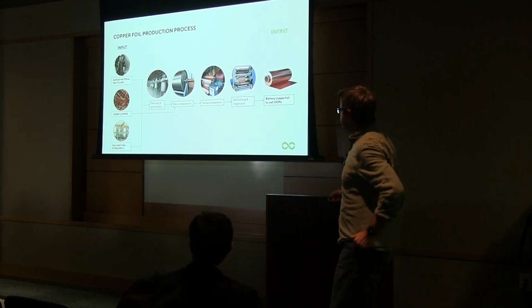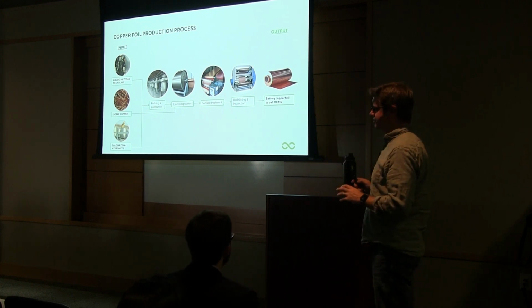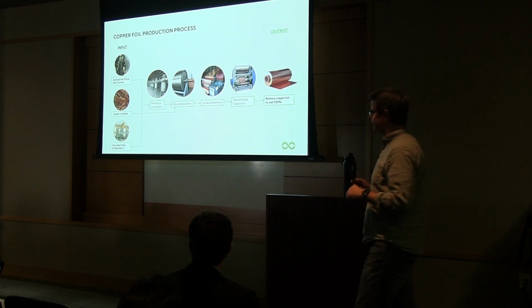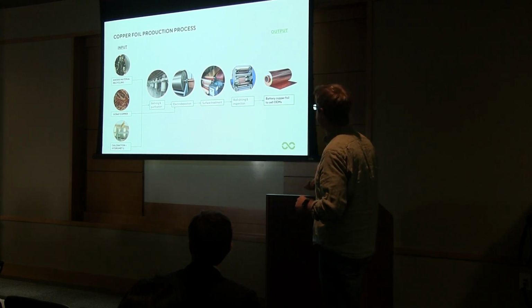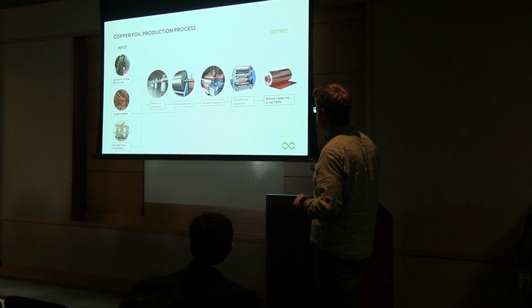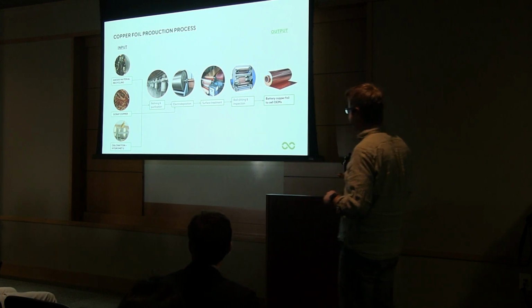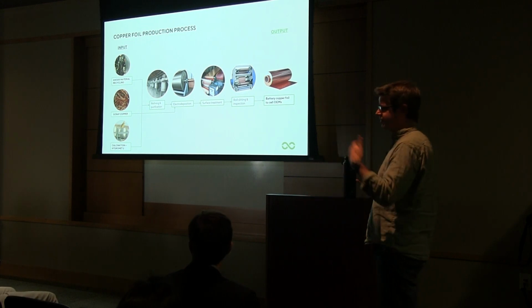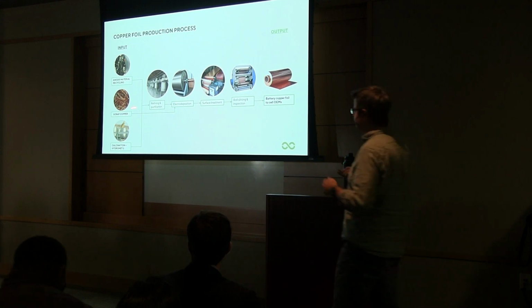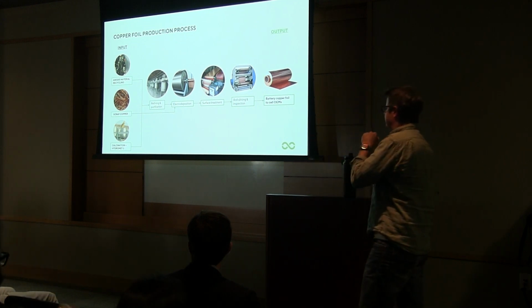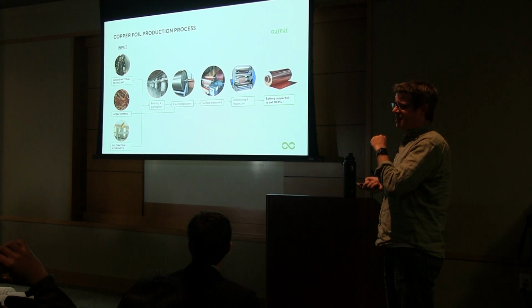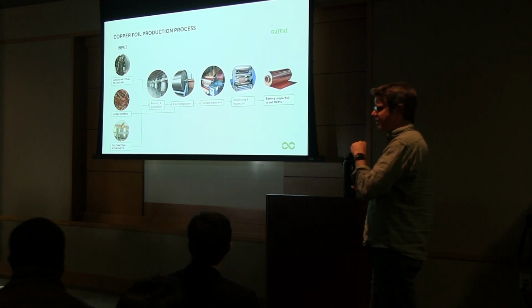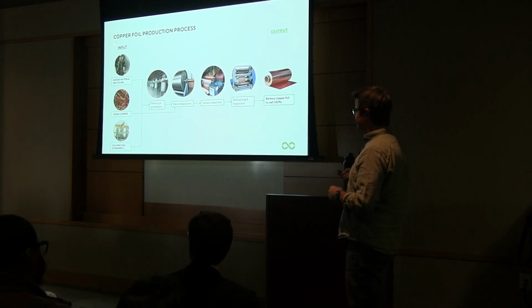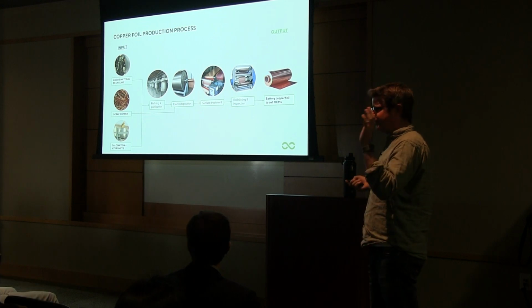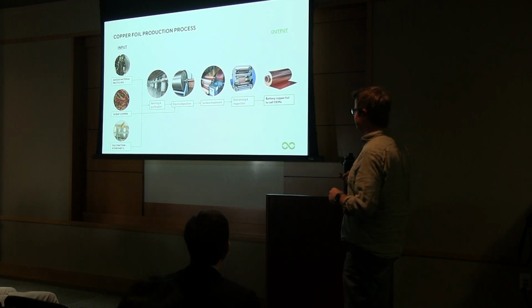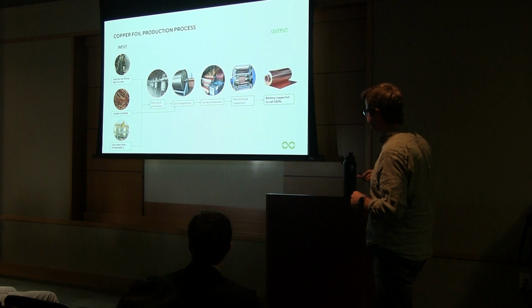The copper foil production process is essentially an electrodeposition process. So it's like an electrowinning process, continuous electrowinning. We're taking anode recycled material, scrap copper, and scrap copper from our recycling processes as well. The US exports on the order of 1 million tons a year of scrap copper. It's pretty crazy. There's a lot of copper available in the US, plenty enough for us to make hundreds and hundreds of gigawatt hours of copper foil, which is great.